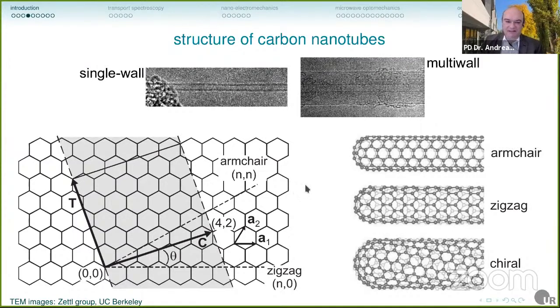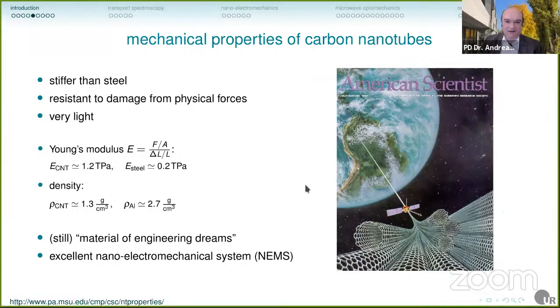Now, people have been fascinated by these nanotubes for many years now, and there are many different reasons for it. On the one hand, the mechanical properties. They are stiffer than steel, they are very resistant to damage from physical forces, and they are very light. And you can quantify this, for example, with the Young's modulus, much higher than steel, with density as the bulk material, of course, lower than even the lightest metals. So this is a material of engineering dreams, as you can also see from this journal cover already from 1997. But also they make excellent nano-electromechanical systems.